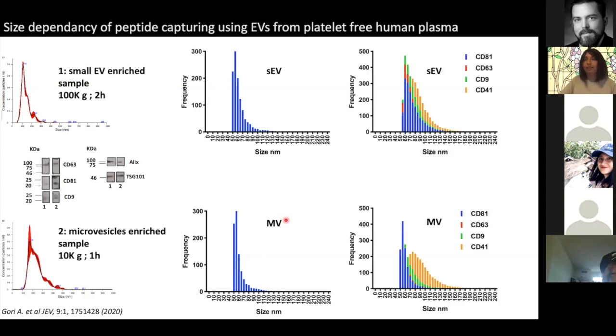And interestingly, this is not the case on the antibody chips. These are the antibody chips with CD81, CD63, CD9, and CD41 immobilized. And clearly the size distributions are wider, and especially interesting is the size distribution of vesicles captured on CD41, which, as far as I read in the literature, is a marker related to platelet-derived microvesicles. So especially on these antibodies, the size distribution is much larger compared to what is captured on the membrane sensing peptides.